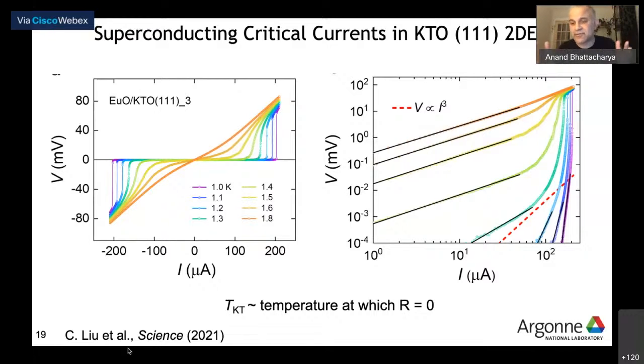So we are restricted in temperatures. In our data, you will often find that we never measure critical currents below a Kelvin if our samples have a higher TC. So far, we explored the region near TC fairly well, and we think we can explain many of the things we see